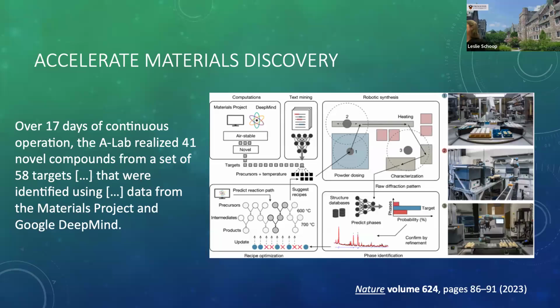And just to know how it works, the AI came up with a synthesis recipe based on reading the literature. The robots put materials into a mortar, made the materials, put them in a furnace, took the samples out, reground them, put them in a furnace again, and then took an X-ray spectrum, and then the AI tried to fit the X-ray spectrum and decide if the material was made or not. And it made a loop of this. So if it really made 70% of those target compounds within 17 days, that would be a big deal, and would also mean that this materials prediction paper is actually better than we thought.